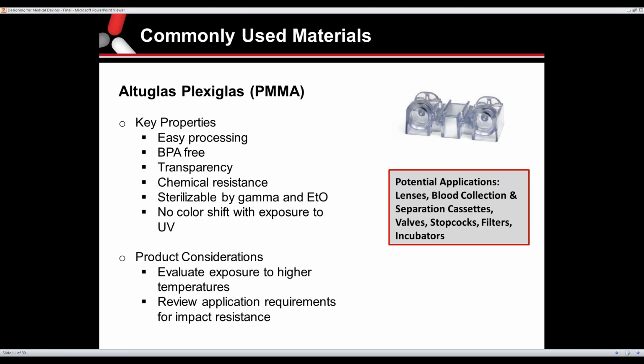The applications that are real good fits for the acrylic material would be lenses. A lot of the blood collection and separation cassettes are molded with acrylic material, as well as valves, filters, and incubators. And on the tooling side of it, as this is a little more brittle of a material, you always want to use your best design practices as far as wall thicknesses, where you're gating the part, and make sure you have no sharp corners.